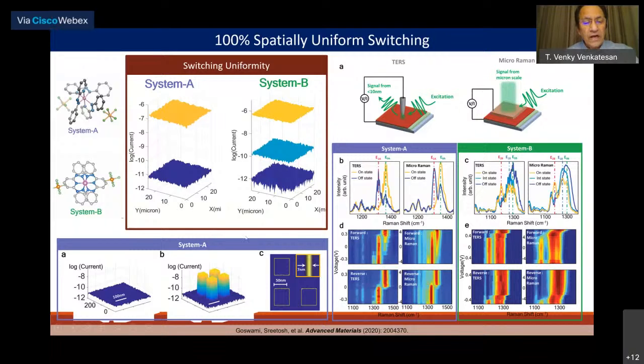These are actually patterned electrodes, and other devices that are in pattern. They're down to about 7 nanometers, and the molecular size is 1.5 nanometers. We believe that is the ultimate limiting size for devices we can make with this system. And these are Raman spectra, but obtained with tip enhanced Raman spectra, so that we can actually look at the Raman spectrum at a molecular level, basically. How is the behavior at a molecular level? The answer is, if you compare the Raman spectra on the switching with the micro Raman in the large area device, they're identical. So there's no difference at all in the mechanism right down to the molecular level.